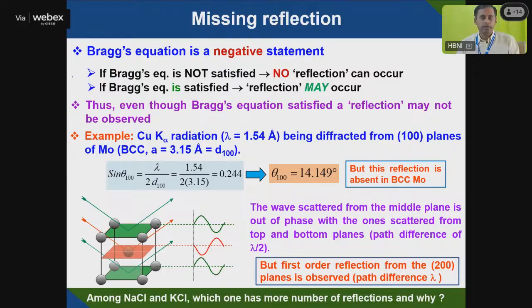But when you go for an X-ray diffraction pattern, sometimes you see there are missing planes. You are not getting all the peaks. As you know, Bragg's equation is a negative statement. That means if Bragg's equation is satisfied, you may get a reflection. But if Bragg's equation is not satisfied, there is no reflection. That doesn't mean that if Bragg's law is satisfied, you will always get a diffraction peak. That is not the correct statement. Thus, even though Bragg's equation is satisfied, a reflection may not be observed.